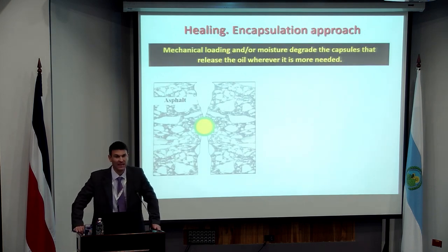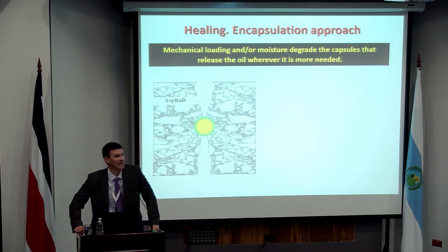So the first thing is it has to be able to release whatever that healing agent is at the correct time. And that can be done through a number of different processes. At the moment, we're looking at two different processes. Either there is some kind of mechanical unlocking of that capsule in terms of when damage occurs at a certain level, the capsule cannot maintain its integrity, it breaks and it releases the fluid into the asphalt material, which allows it to heal. Or we can have it activated by a change in the outside coating of the capsule when it is subjected to moisture.